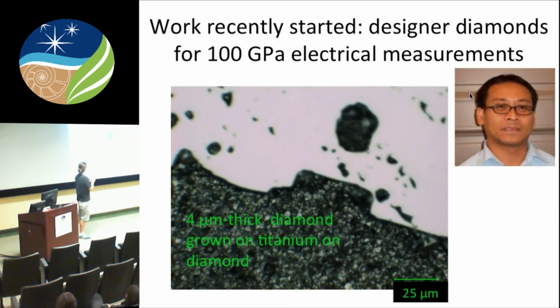Those are the things I want to do in the near future. And then Kadek and I have started a collaboration that's much more general than just heat capacity. We're trying to make designer diamonds like the other groups have, but in our own way and with new features. So I've deposited titanium on diamond, and now he's grown diamond on top of the titanium. So it's a diamond, titanium, diamond sandwich. And he's trying to make nanocrystalline diamond for thermal insulation. Really fancy things that hopefully one day will open up opportunities to measure heat capacity at really high pressures, and to make electrical transport measurements at high pressures, things like that.